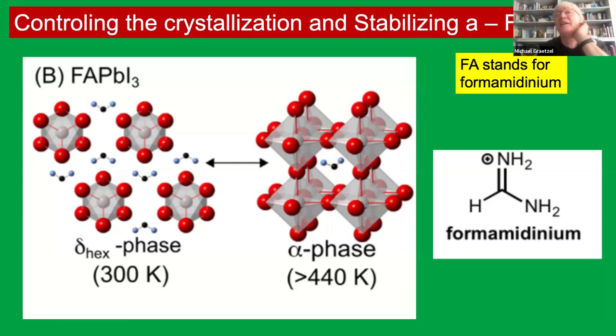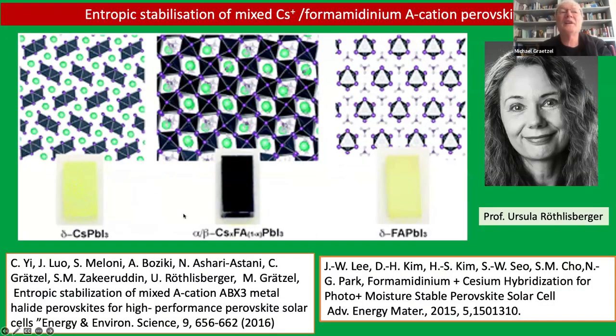And so, yeah, it doesn't serve any purpose if you have a photovoltaic material that converts to an ineffective phase, a phase that is not only photovoltaically ineffective, but also produces recombination reactions. And so you don't want this in a mixture. So how do you maintain this alpha phase? It was discovered that when you mix A-cations like cesium and formamidinium, then you can stabilize the black phase.